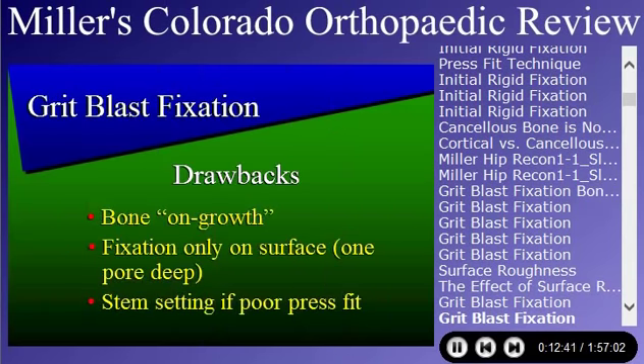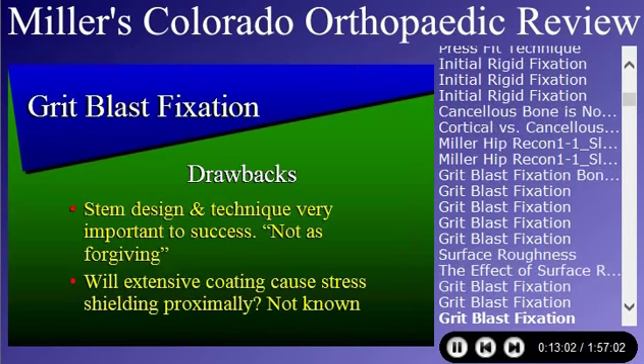Again, the drawbacks of these are it's bone on-growth, it's not in-growth, so the interface is not as strong. The fixation basically is a half pore to 1 pore deep. And if you don't wedge it in good technically, you're going to have stems settling. And that's the main drawback with press-fit grit-blasted stems. So in grit-blasted fixation, stem design and technique are very important. It's not as forgiving as the porous-coated implants. The long term is what we don't know: whether these extensively porous-coated or grit-blasted stems will stress shield. Probably not like the big AML porous-coated stems.